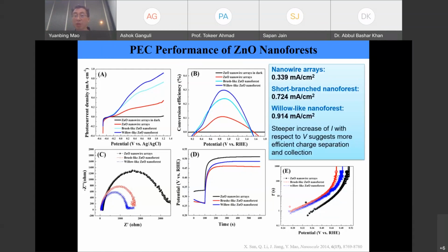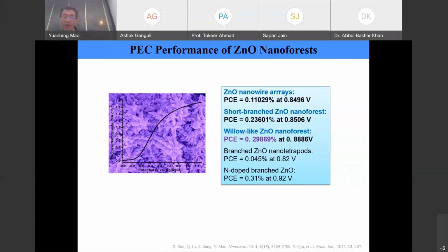So if we really want to put this into numbers, you will see that in terms of the photocurrent density, this willow-like nanoforest is almost 3 times that of the nanowire arrays. So that means we can increase the photocurrent density by 3 times. And if we compare with the literature data, even though our zinc oxide nanostructures are not doped, just pure zinc oxide, the PCE is almost the same as the nitrogen-doped branched zinc oxide. So that really gives us confidence about this type of nanoforest. It really can improve the PEC performance.